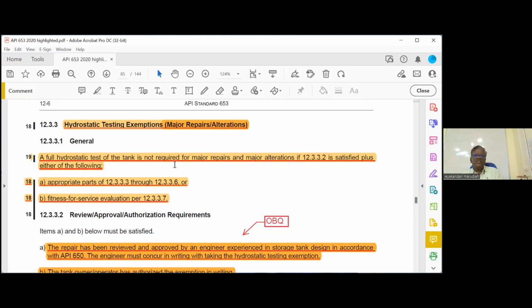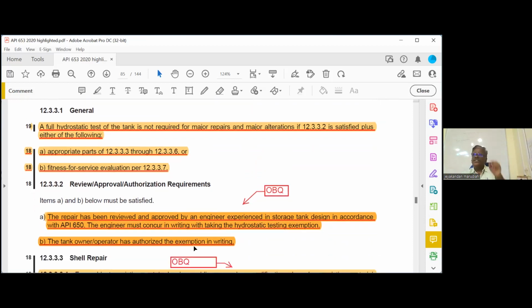See, a full hydrostatic test is not required for major repair or alteration if 12.3.3 to 3.2 is satisfied. This is the one the engineer has to write and the owner has to accept, plus either of the following. Either of the following means you have to follow 12.3.3 to 3.6, or we have to go for fitness for service. If you are going for fitness for service, there is no need for hydro test, only for major repair and alteration. Again, I will repeat, for severe service, hydro test is mandatory. For reconstructed, hydro test is mandatory. Either you go for fitness for service or satisfy 12.3.3 to 3.6.